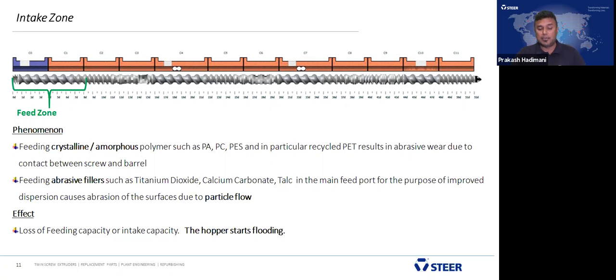Feeding abrasive fillers, such as titanium dioxide, calcium carbonate, and talc, if you feed from the intake for the purpose of improving dispersion, causes abrasion, meaning abrasion of the surface due to the particle flow. What is the effect when you feed it from the intake? The feeding or intake capacity drops, and the hopper starts flooding. In compounding, we often say the hopper started flooding. There may be many reasons: maybe the lower bulk density of the material, or maybe wear and tear in the first screw section, because of the abrasive nature of the filler.